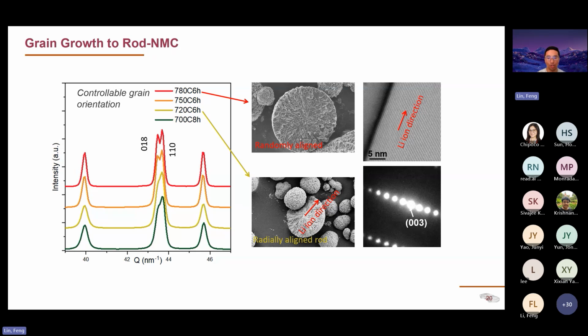And as I mentioned, the grain growth is important. The grain growth is also very sensitive to the temperature profile. So here is an example of two different types of grains. If you do that at 720 degrees C for 6 hours, you get radially aligned grains. If you do it at 780 degrees C for the same number of hours, you get randomly aligned grains. They have the same chemical composition and almost the same lithium content in the final active material, but a 60 degrees C difference can already provide a huge difference in terms of the microstructure. So this is another reason that we need to look into the temperature much more closely.